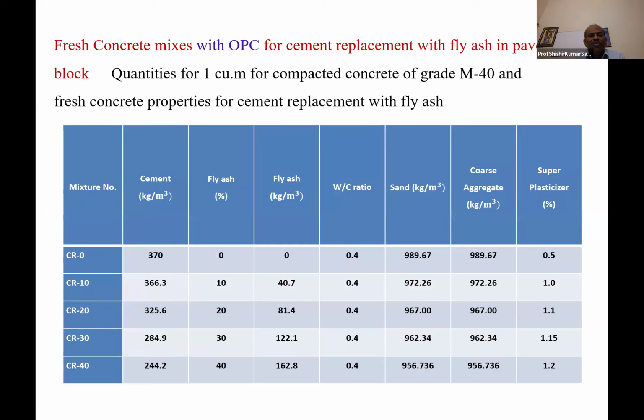Then fresh concrete mixes with OPC for cement replacement with fly ash in paver block. Grade M40, this is the cement quantity. Then this is 10%, 20%, 30%, 40%. This is the material, fly ash, in different percentages that go on increasing. Water cement ratio is kept fixed, 0.4. Sand, coarse aggregate, and this is the admixture.